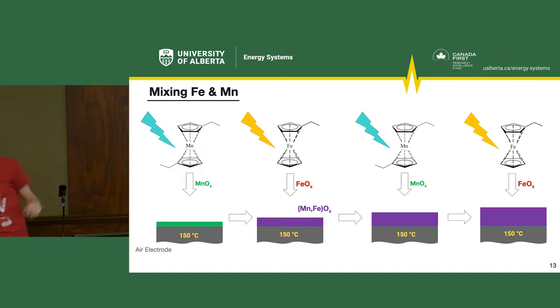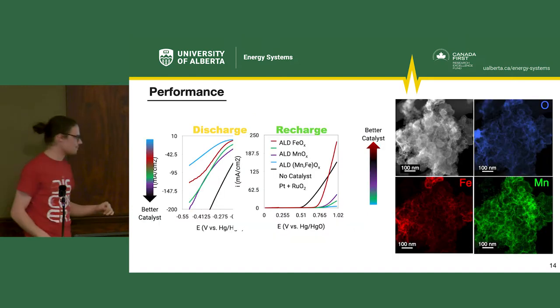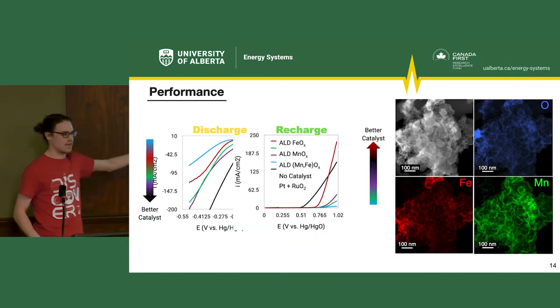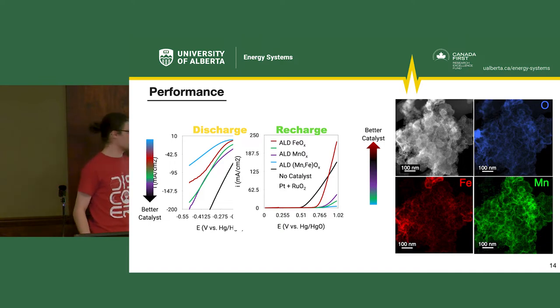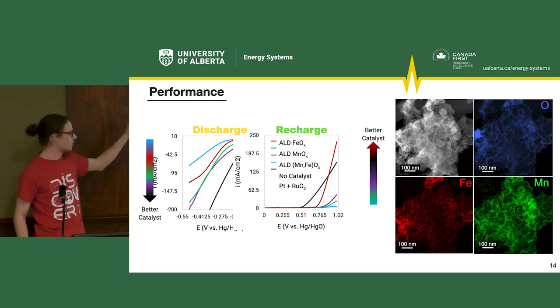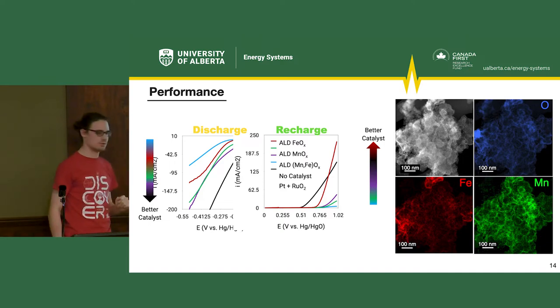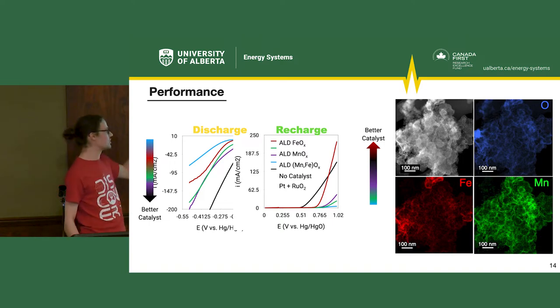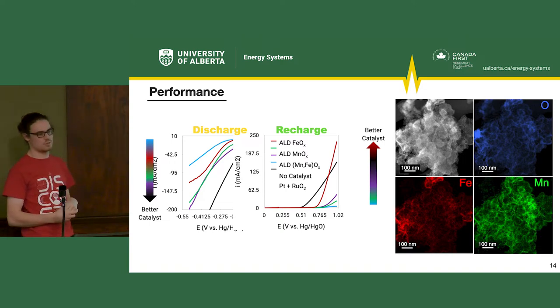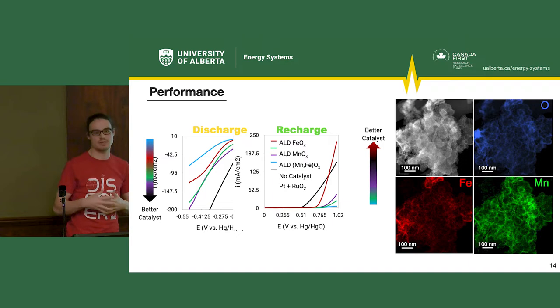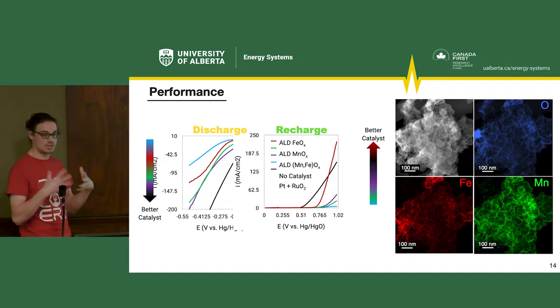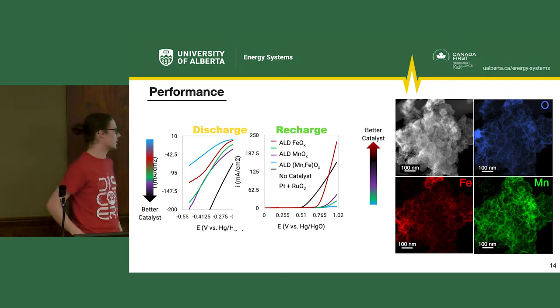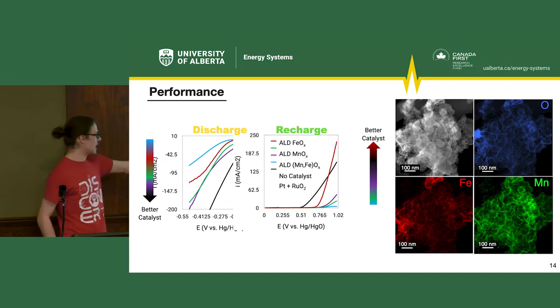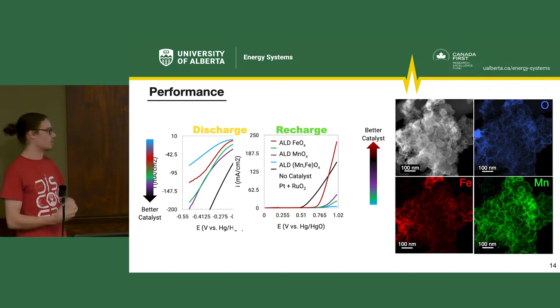So I did just that. And we look at the results. Looking at the discharge reaction, right, energy out of a battery. Red's my iron. Green is just manganese by itself. Purple is that mixture. So somehow we've actually improved the discharge better than either on their own. So we have something called a synergistic benefit. They work together as a mixed oxide to be better than themselves. Platinum's in the black, so we're close to platinum. We're doing a pretty good job here.